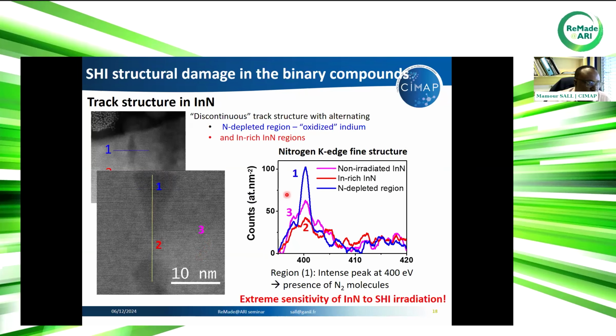Okay, we did the same. So we also recorded the fine structure in region 1. And what we can see here is a new peak in the fine structure that appears at around 400 electron volt. This peak is known to be due to nitrogen molecules. So in fact, in region 1 here, we have nitrogen gas bubbles that are created by irradiation.